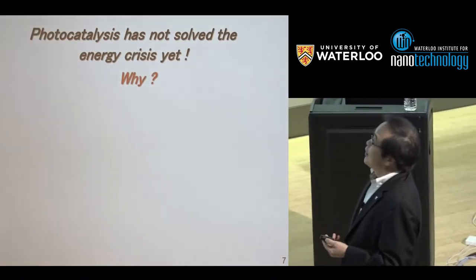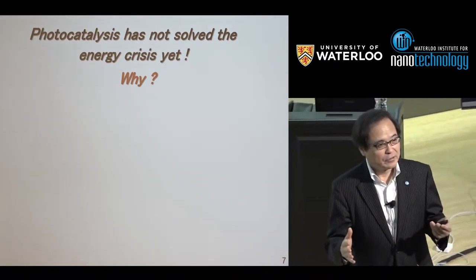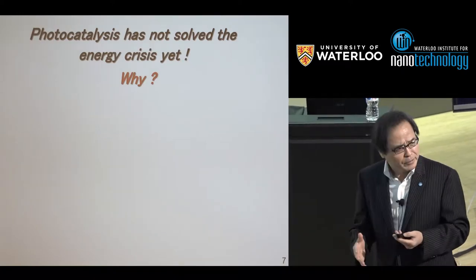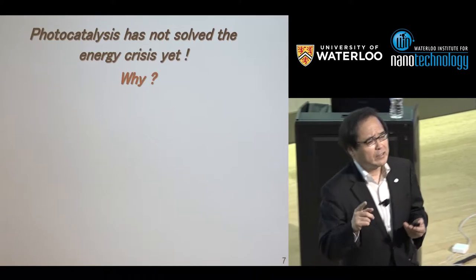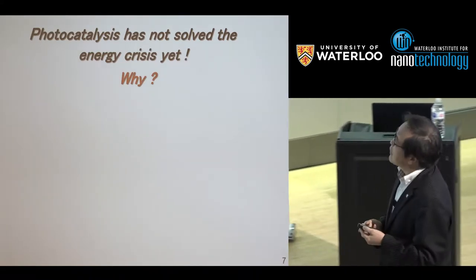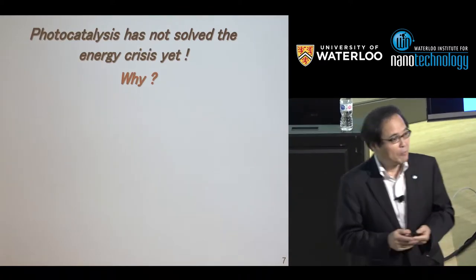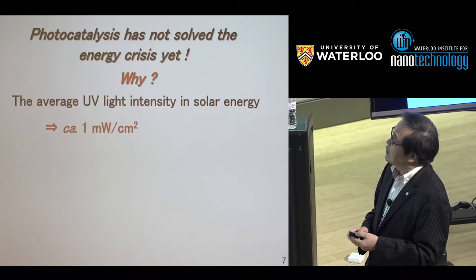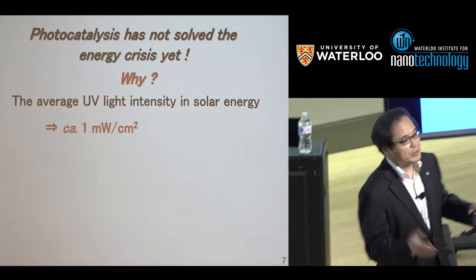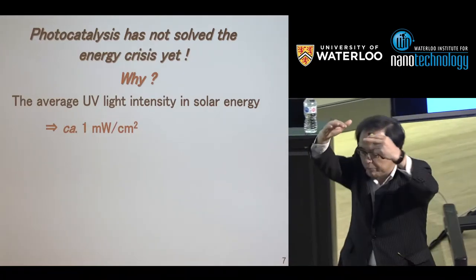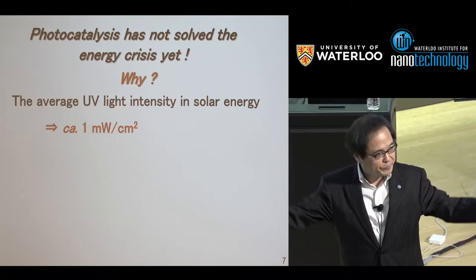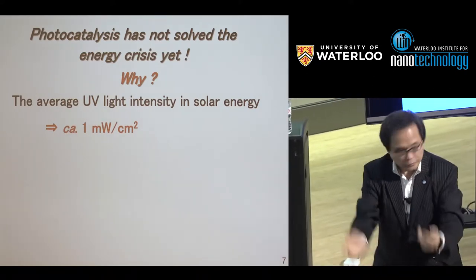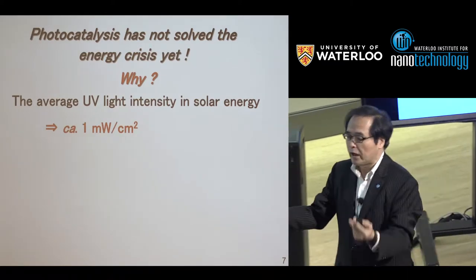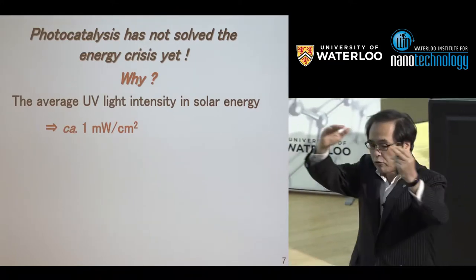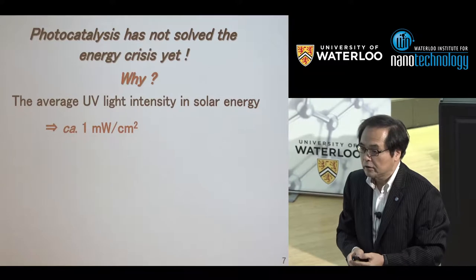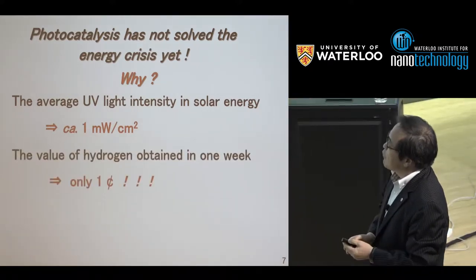So, however, 40 years have passed, that was 1980, but photocatalysis has not solved the energy crisis yet. Why? The average UV light intensity in solar energy is about 1 milliwatt per square centimeter. Okay, so we use a big, huge Fresnel lens, and the bottle is illuminated for 1 week. Huge amount of hydrogen was produced. The quantity, it's huge, but how much is it? The hydrogen obtained in 1 week is only 1 cent.